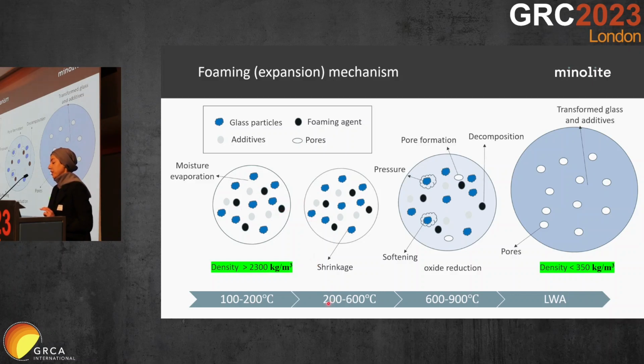At higher temperature, around 200 to 600 degrees C, we have the shrinkage of this particle because the moisture is evaporating. And then after that, at higher temperature, 600 to 900 degrees C, the glass particles start to soften. And also the foaming agents start to decompose. So this is the oxide reduction, and gas is generated from these chemical reactions, and this gas forms pores inside the particle, which you can see in the final product, which is expanded particles here.